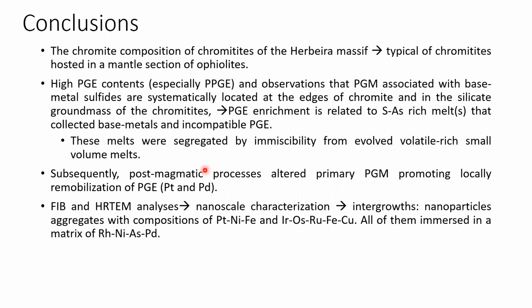Finally, the FIB and high-resolution TEM analysis shows that this complex grain that I showed before has nanoparticle aggregates with composition between platinum, nickel, iron, and iridium, osmium, ruthenium, iron, and copper, all of them immersed in a matrix of rhodium, nickel, arsenic, and palladium.